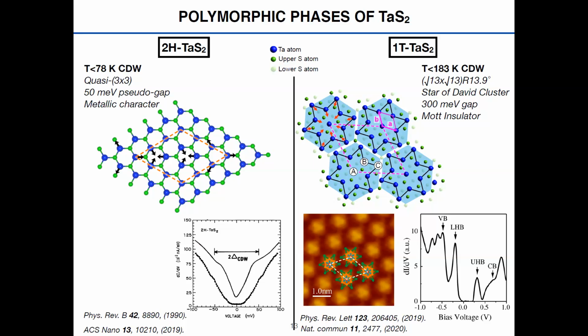Also, when you go below 0.8 Kelvin, it has a superconducting transition, but we're not going to be able to go there, so it's not important for us. The 1T phase has a much richer charge density wave phase diagram. It has many charge density wave phases. The one we're going to see today is below 183 Kelvin, where this root 13 by root 13 charge density wave, rotated 13.9 degrees, appears.